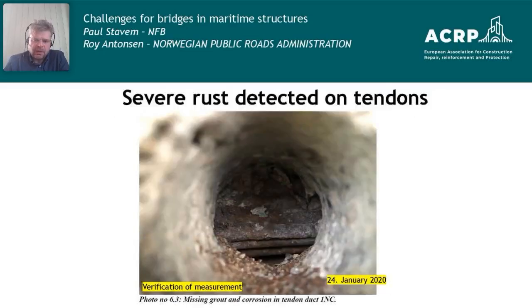Very scary results we found there, and therefore when we verified the results, we actually took a 32mm drill and drilled straight onto the tendons. We would never do this because we're always afraid of damaging the tendons, but this time we had to verify our measurement results. As you can see here, this is a red zone. We measured with ultrasound and all these methods saying that it was empty, and it was empty. So we verified the measurement methods, and notice also that we did not damage the tendons inside. There's a lot of corrosion in there, and therefore we verified our suspicions on the voids there.